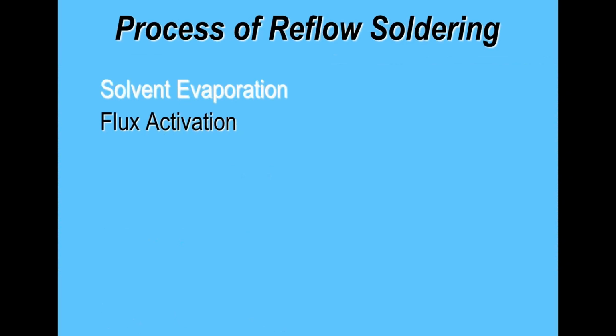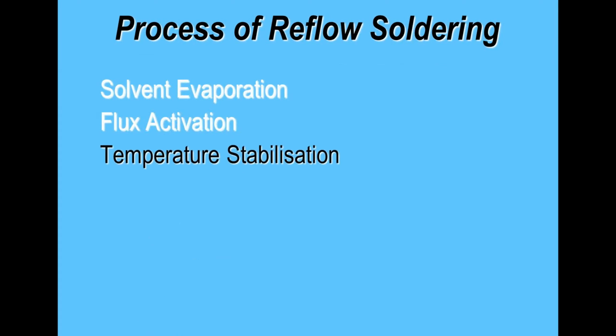Flux activation. Now, the flux in a solder paste, we need heat to activate the material, but if we have too high a heat for too long a period of time, we can deactivate the flux. This is particularly true with no clean materials or very low solids materials, i.e. the flux content of the overall solder paste. And we can get issues of poor wetting related to flux activity. But if you follow the recommendations of the paste manufacturer today, these are more accurate recommendations, I would suggest. Originally, most profiles supplied with suppliers were very general and very consistent between each supplier. Now, most supply more detailed information.